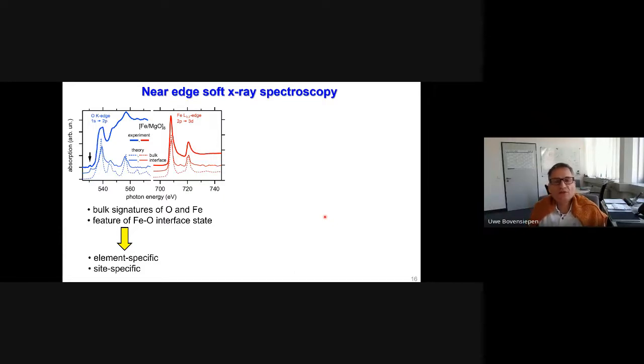So let's look at the soft X-ray spectroscopy without pump excitation at first to understand what we actually start with. So here at the left, you see the absorption at the oxygen K edge. This is the 1s to 2p transition. And you see here the pronounced fine structure of the bulk oxygen K edge absorption in MgO. There is theory, which I mentioned already by Markus Gruner and Rossitza Pentcheva for bulk and interface. And you see here these contributions. And I would like to highlight this small peak here in the pre-edge region. This is a signature of an interface state.